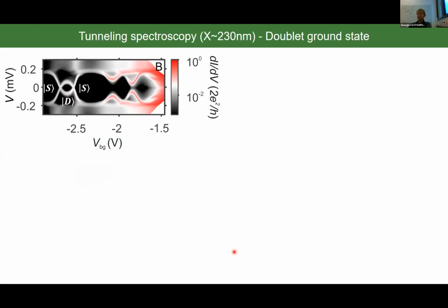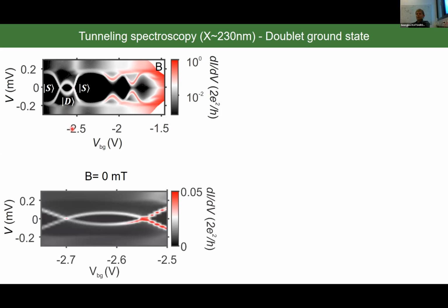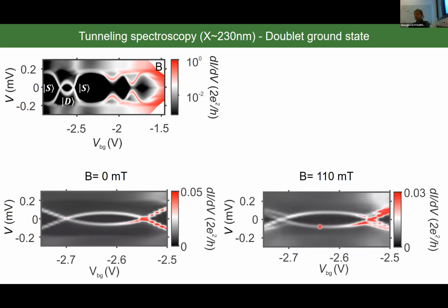So let's see how our devices behave when we have a quantum dot in the tunnel junction. We measure differential conductance versus bias and backgate voltage, and you can see beautiful Andreev bound states. You can see the characteristic loop-like feature, which is a fingerprint of a doublet ground state. And we will focus first on this regime. That's the same plot, but at zero magnetic field, zoomed in. If now you crank up the magnetic field and we focus again on the doublet ground state, what you can observe is that the energy of the Andreev bound state has increased.